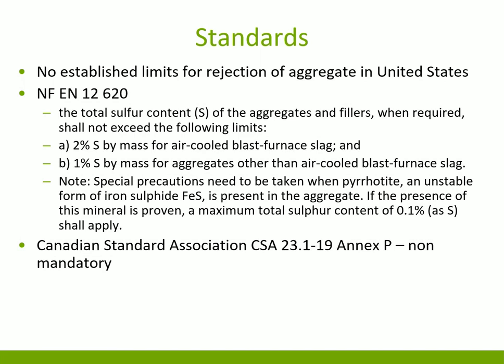So part of it is a performance evaluation for the determination of deleterious oxidation potential of sulfide-bearing aggregates. The first part, you're going to do a field evaluation of the aggregate source with the geological survey and sampling, some field performance in concrete. If you have concrete that's more than 15 years old that was using the same aggregate in an oxidating environment, you can test that to evaluate if a reaction is occurring or not. And then the last part is a laboratory investigation and interpretation.